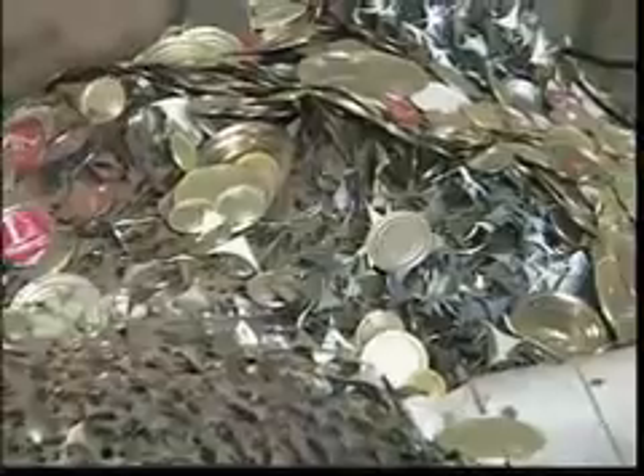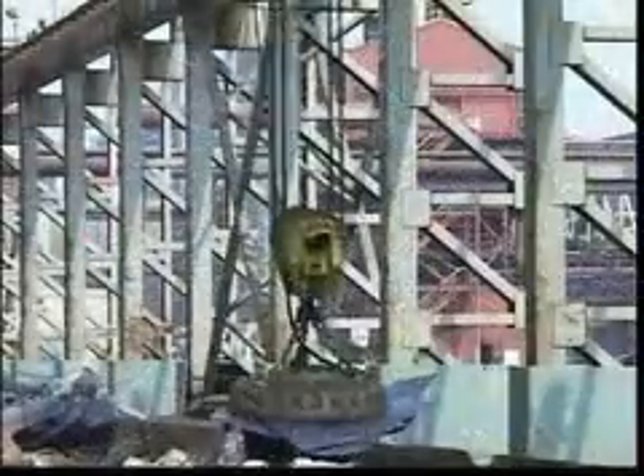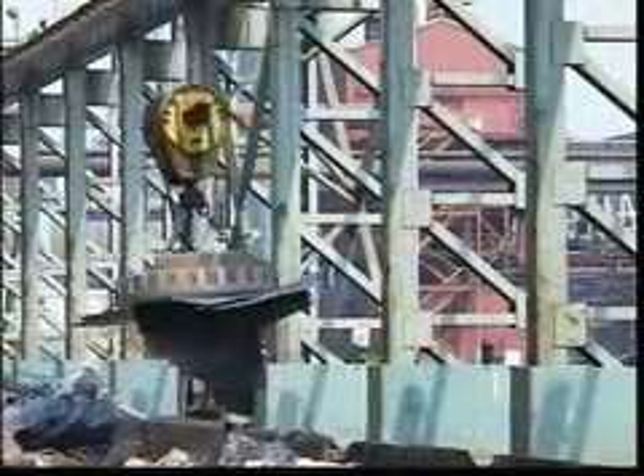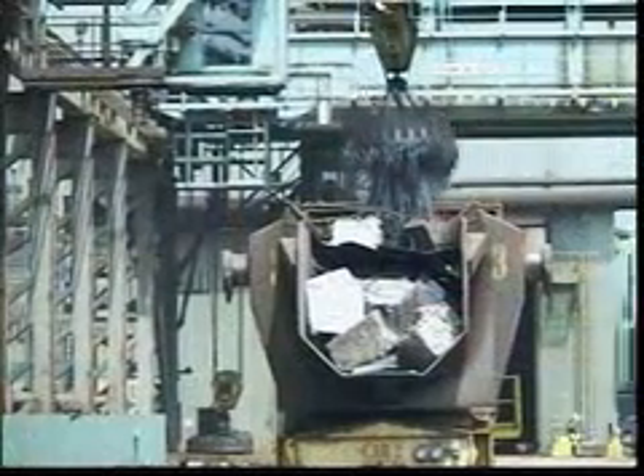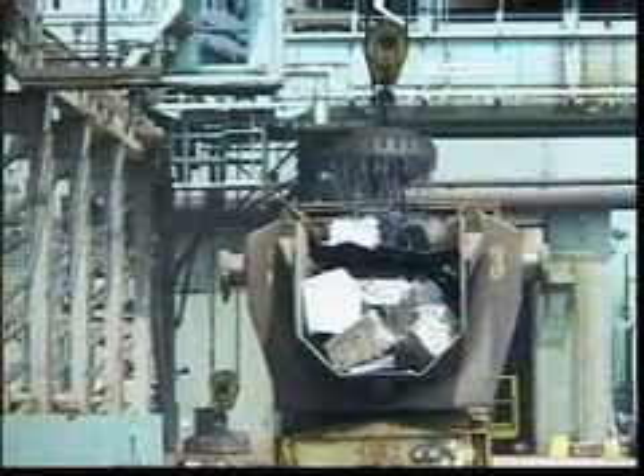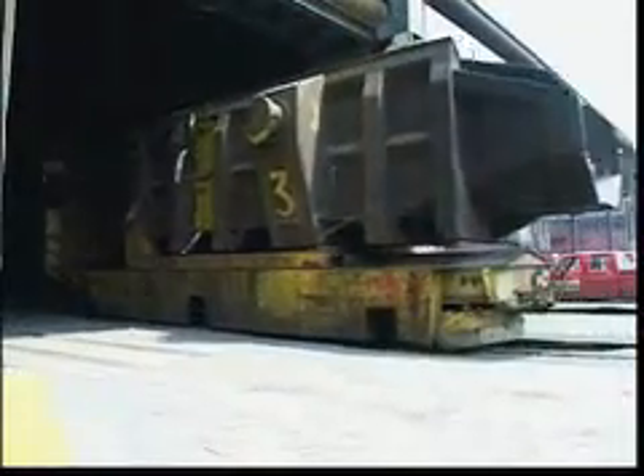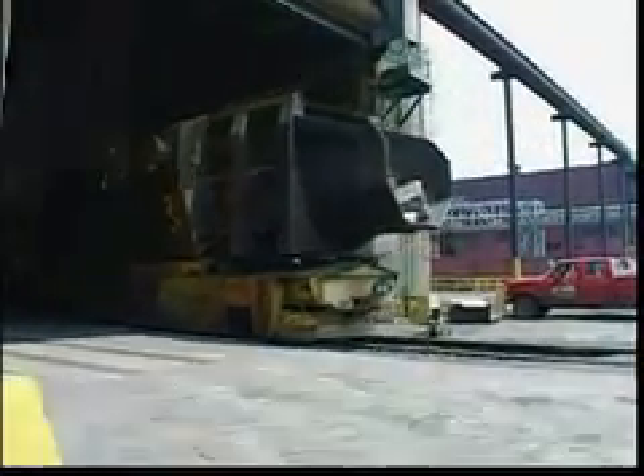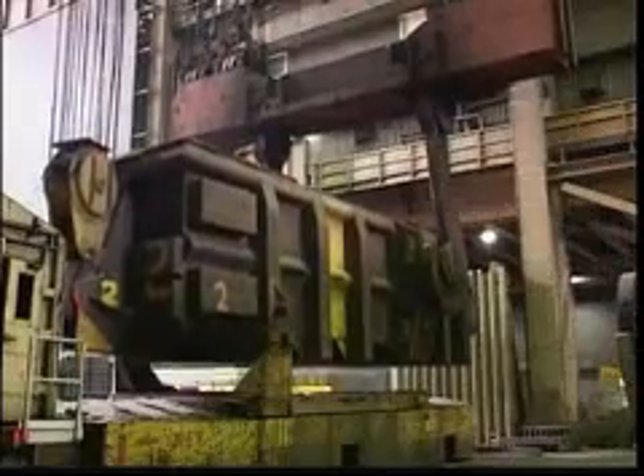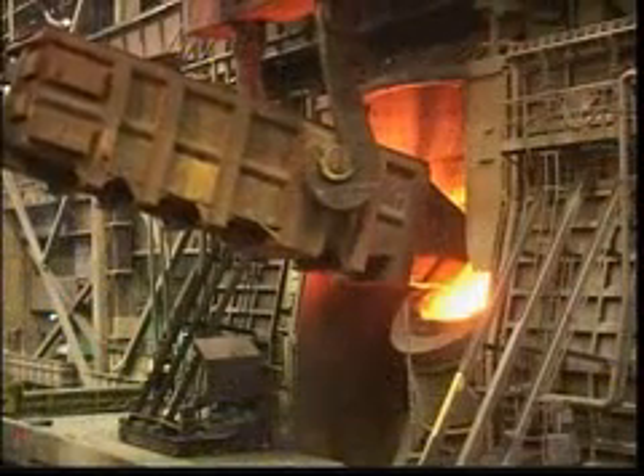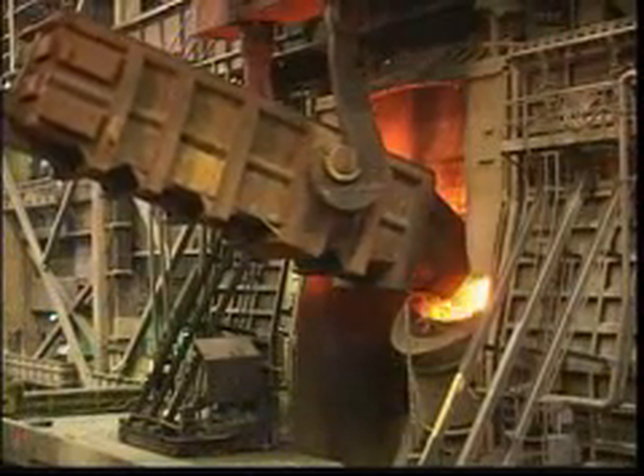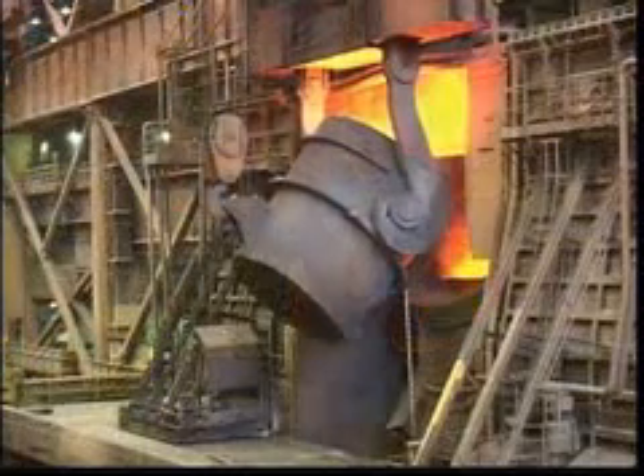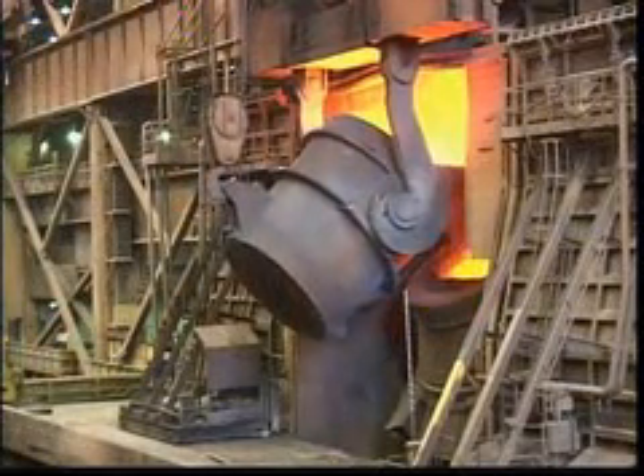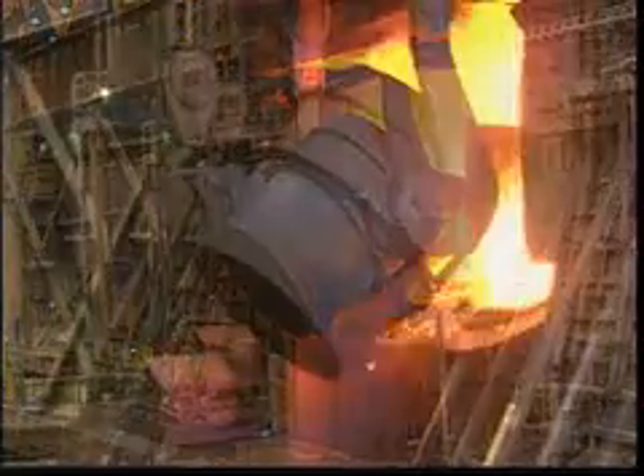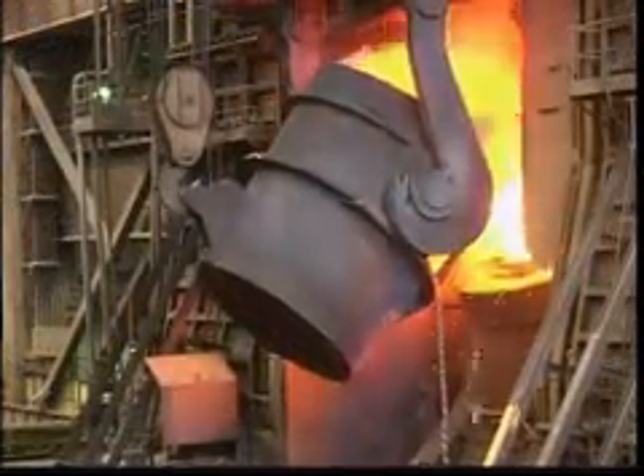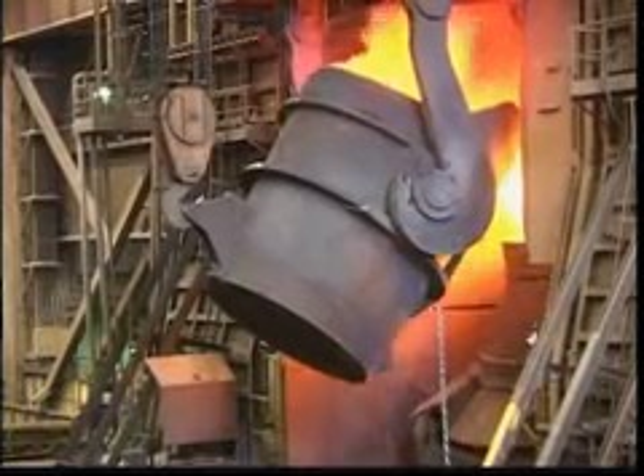At a scrap handling yard just outside the KOBM facility, magnetic scrap cranes distribute the correct mixture of different grades of scrap into bins that move into the steelmaking facility on transfer cars. A crane then lifts the container up to the 325-ton KOBM vessel. After the scrap is loaded into the furnace, another crane pours in the molten iron. The furnace then returns to an upright position, and pure oxygen is injected from the top and bottom to melt and refine the mixture inside.